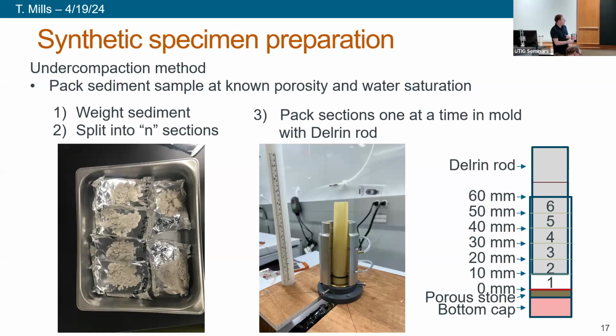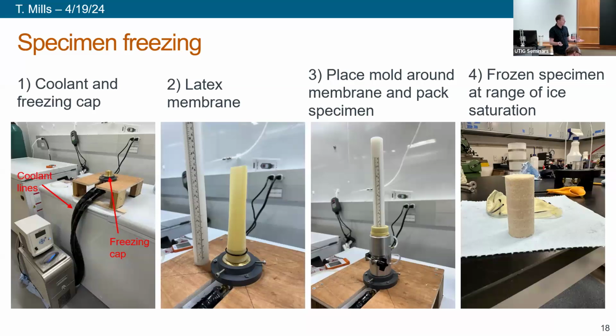And so we had to think of a method that we could use to try and build a synthetic permafrost sample that didn't let the water drain to the bottom. And so what we ended up deciding to do is we took this freezing cap and we inverted it in our lab. And we have coolant lines running from a chiller. They go up through this brass cap, and the chiller runs this coolant at like -8 degrees Celsius. And then we can put our latex membrane over this cap, put our mold around it, and then start to pack our sample.